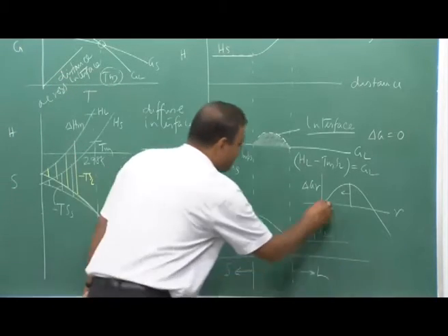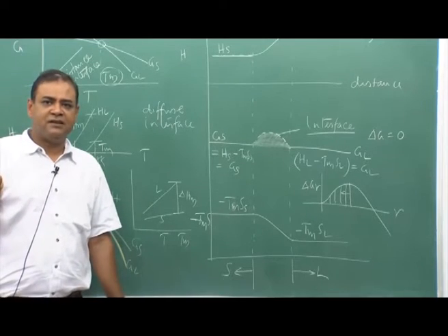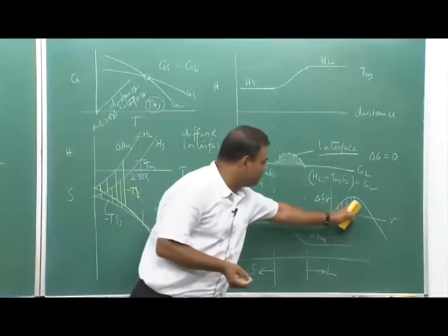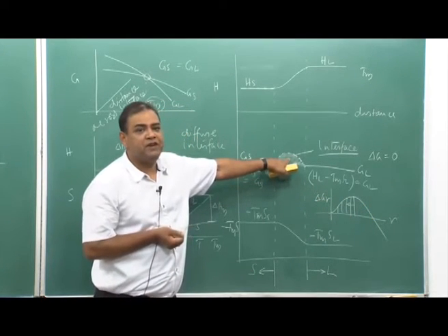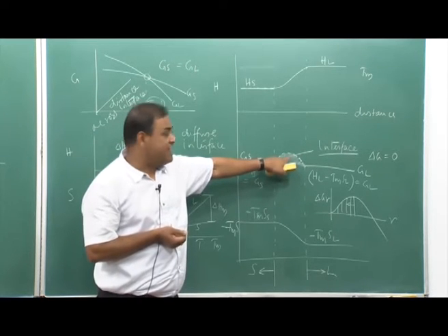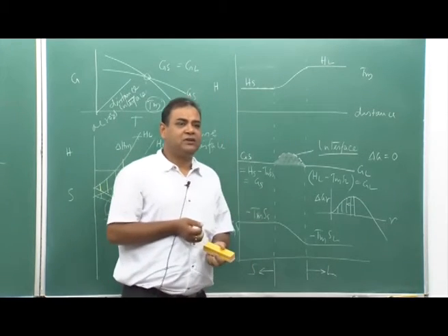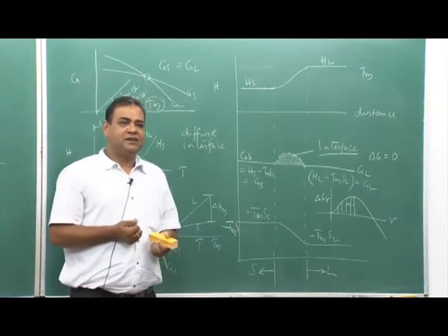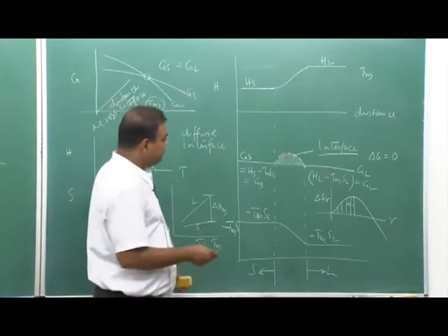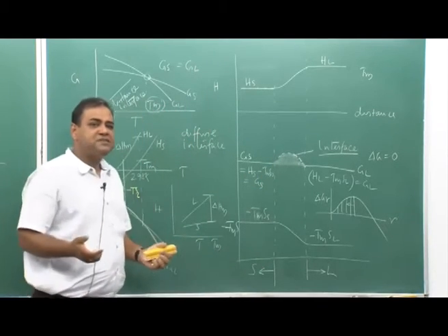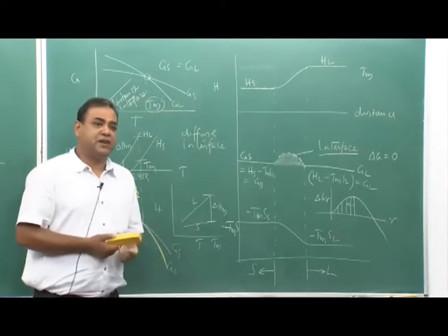So, as a function of r, there could be a lot of solid-like clusters, but they cannot go beyond this, because in all cases I have a positive contribution of the interface, and this interface will not allow the free energy requirement for stable nuclei formation. So, we can clearly see that interfacial energy is giving a positive contribution to the overall energy scenario.